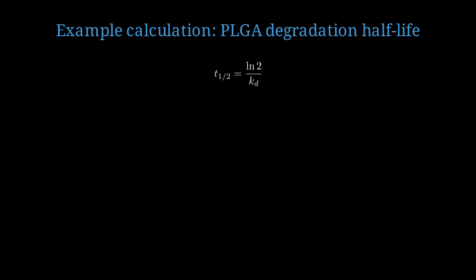The half-life is natural log of 2, divided by the degradation rate constant Kd. For PLGA with a 50-50 ratio of lactic to glycolic acid, Kd is typically around 0.01 per day at body temperature. So T half equals 0.693 divided by 0.01, which gives us about 69 days. This means the PLGA microcapsule loses half its mass in about 2 months, allowing sustained drug release over this period.